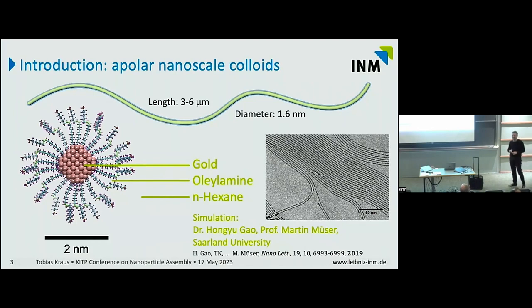There are recent results that suggest that the cores have more complicated structures, and you also see that the shell is actually thicker than the core. So this organic shell here is dominating the behavior of these ultra-thin nanowires. This has also been simulated. You'll see that later by our colleagues in Saarland, Martin Müser, and it's all my fault. I told him to put an FCC here, which is not strictly correct, I suppose.